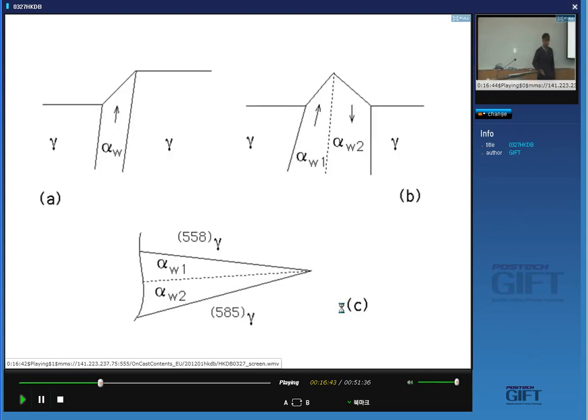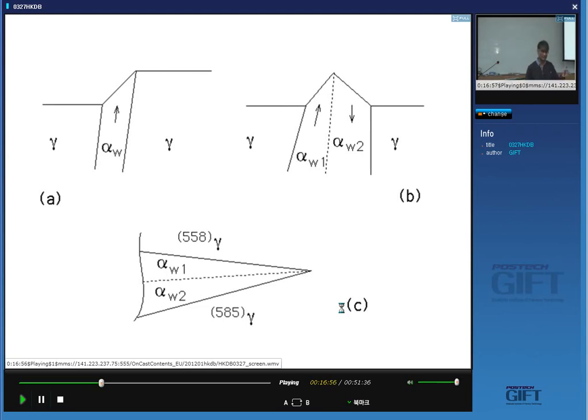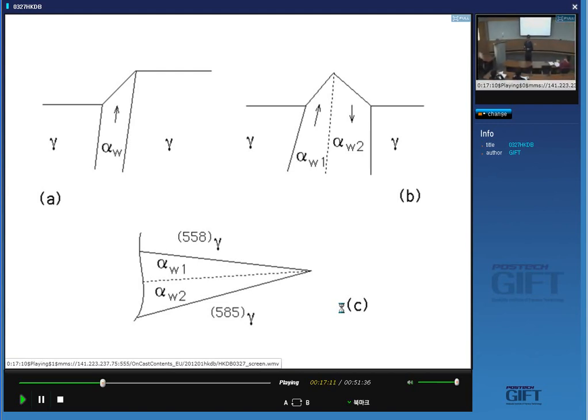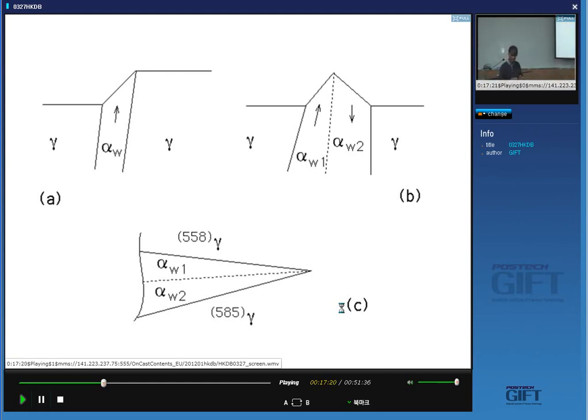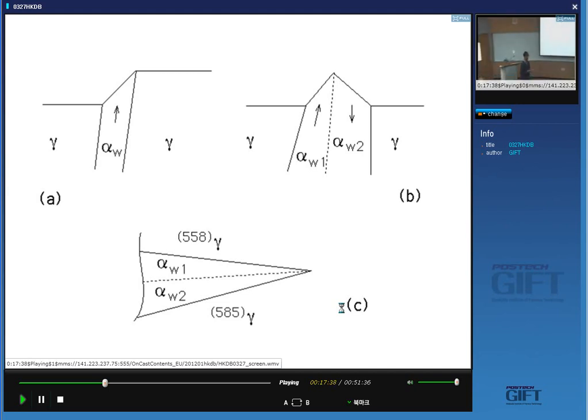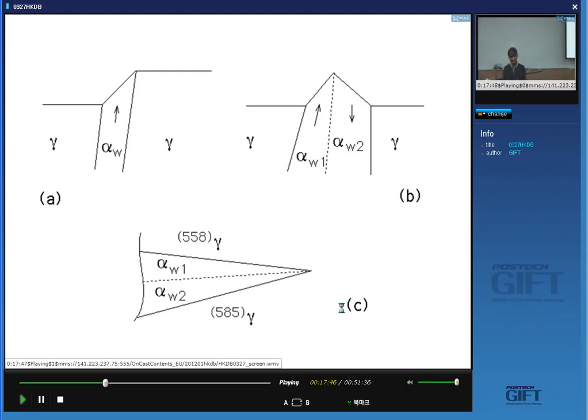What's happening is that if we form a single plate at a time, the strain energy is just too great to allow Widmanstätten ferrite to form at high temperatures close to the A3 phase boundary, because we've raised the temperature and the driving force for transformation decreases and you cannot easily sustain such a large strain energy due to the shape deformation. So instead of isolated plates forming you get two plates forming together in such a way that they cancel out each other's shape deformation.